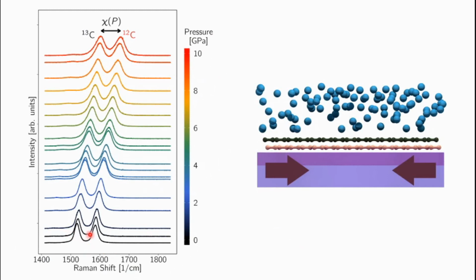Here we show the G-band Raman signal evolution with pressure of the supported graphene layers under high pressure using nitrogen as pressure transmitting medium. The G-band hardens with pressure due to the biaxial compression and the pressure transmitting medium densification. The carbon-12 bottom layer in contact with the substrate has a different environment than the carbon-13 top layer in contact with the pressure transmitting medium, and then the evolution of the difference of the G-band position, which we call chi, can provide information about a mismatch between the two layers.